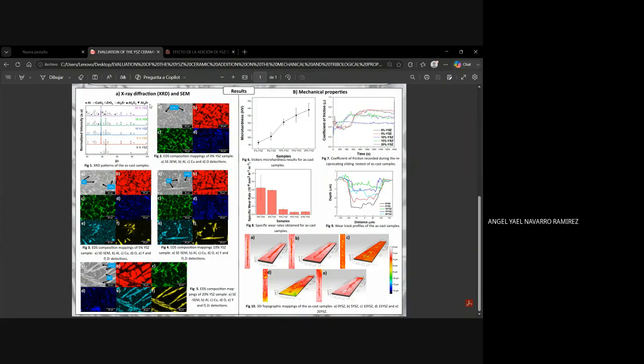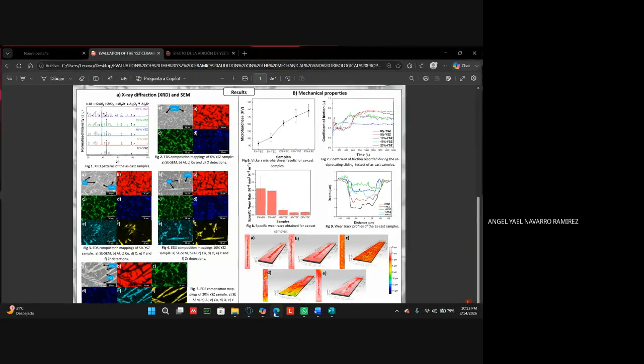And what is the percent of decrease? Between 0 and 15% it is 91%. This is a very big decrease and very good, because it reduces the effect on the surface of the material. Continuing with figure 9, you can see the wear track profiles. You notice that with a higher percentage of YSZ, the depth and the width reduce, except for the 10% YSZ. I repeat what I said about figure 7: this is because when I did this test, the material presented adhesion, not wear. Sorry for that. Continue with figure 10.